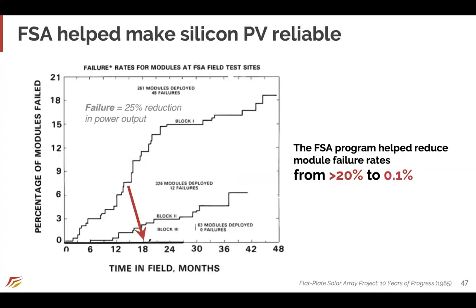And probably most importantly, it helped make silicon PV reliable. So if you look across this program, it helped reduce module failure rates from over 20% to 0.1% in the last block buy. So there's a few possible takeaways for perovskites. Field testing is obviously critical. We need to move from passing the standard qualification tests to understanding how perovskites specifically fail in the longer term, and then design the qualification test to evaluate those failure modes and design solutions to mitigate them.